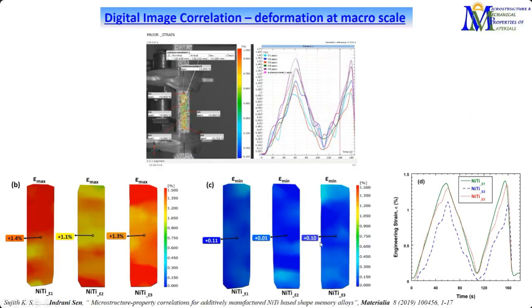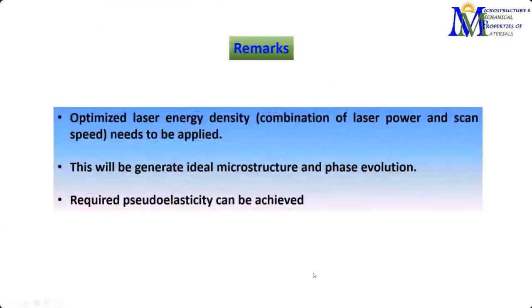And we could figure out that the three distinctly different components produced by different energy densities have different properties. If we simply do normal tensile testing, or simply hardness testing, we will not be able to figure that out, whereas we can find the pseudoelastic nature of this material from its tensile behavior. So the bottom line is we require an optimized, lesser energy density. Instead of low or high, we require a particular optimized value to have completely pseudoelastic behavior along with a more or less ideal microstructure and phase.